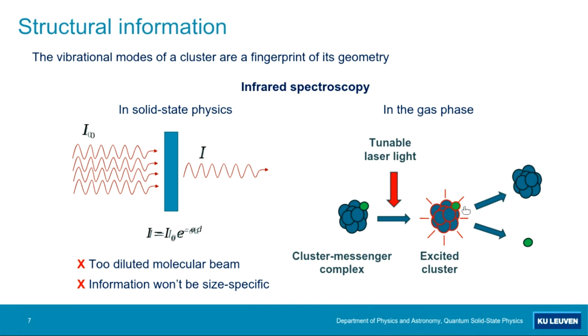And because it's isolated, all that extra energy gained by the photon absorption has to be somehow released. But remember that this particle is in vacuum, so it cannot interact with any gas, with anything. So the only way it will release that energy is by fragmenting. And this fragmentation process is really like the particle will kind of explode. By this explosion, the mass changes, of course, and that is something we can know from mass spectrometry, how the masses of the particles are changing. And this we can know as a function of size because of the scheme of time-of-flight mass spectrometry.